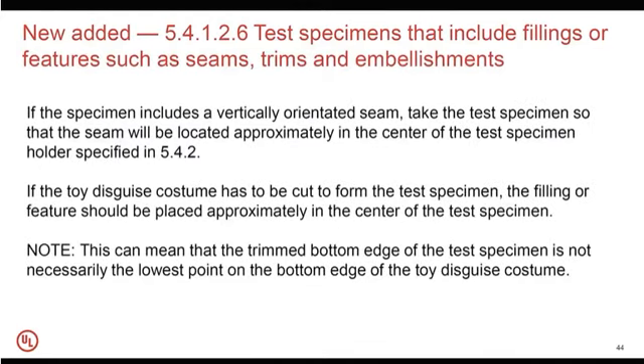If the specimen includes a vertically orientated seam, take the specimen so that the seam will be located approximately in the center of the specimen holder, which is specified in point 5.4.2 of the standard. And if the toy disguise costume has to be cut to form the test specimen, the filling or feature should be placed approximately in the center of the specimen itself. So this can mean that the trimmed bottom edge of the test specimen is not necessarily the lowest point on the bottom edge of the toy disguise costume.